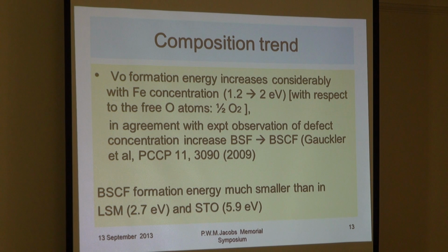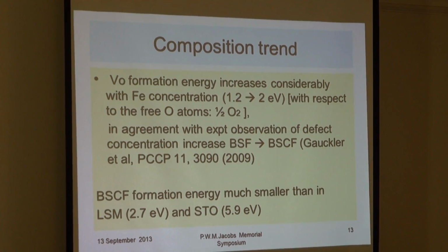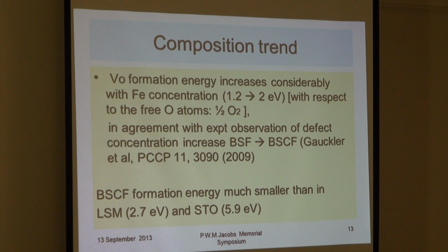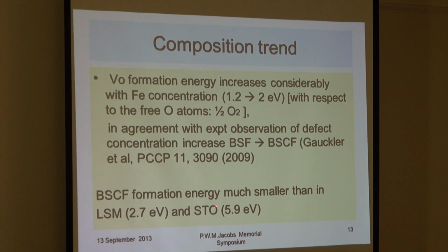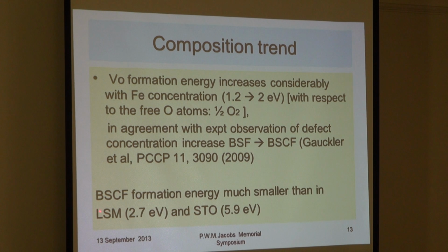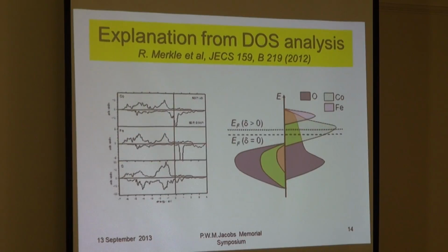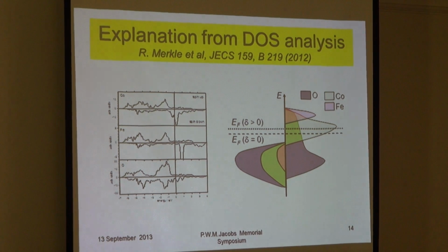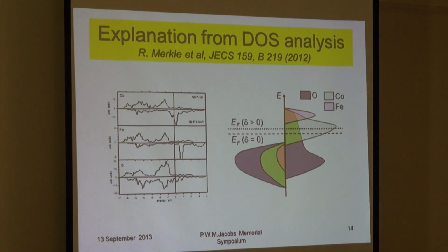But also what I would like to stress is that these so low formation energies explain why it's so much non-stoichiometric at high temperatures, operational temperatures, like 1000 Kelvin. For instance, in strontium titanate, a standard perovskite, formation energy is about 6 electron volt for a vacancy. And for lanthanum strontium manganite, it's about 3. And here it's again much smaller.